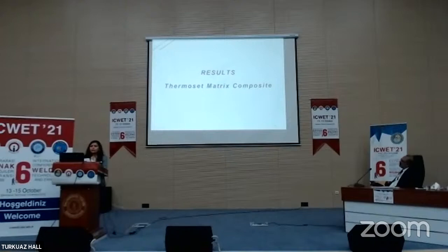Here are the results of this study: physical and mechanical test results of thermoset matrix composite panels. All setting parameters were determined before the experimental studies on the composite surface. First of all, thermoset matrix composites, which are manufactured from fine satin fabric having 2 mm thickness, are treated by Nd:YAG laser. The first study is done by keeping wavelength, frequency, scanning speed, and pulse distance parameters constant. Focus distance is adapted at different laser power. After laser scanning, surface wettability is analyzed by optical tensiometer to find the optimum focus distance.